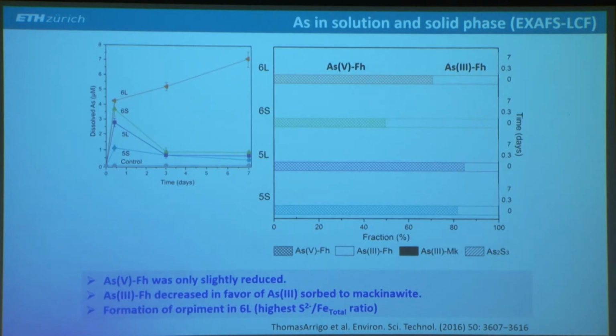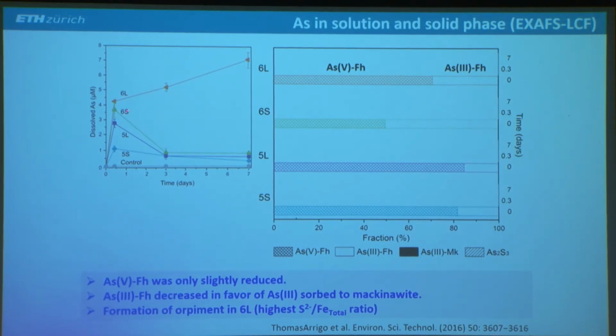If we look at arsenic, we also see a fast increase in dissolved arsenic in solution in all 4 flock samples. But in 3 samples, it decreased again. In the control, there was no arsenic release. And we had 1 sample where it continued to increase. We'll come back to this in a second. If we look at the solid phase speciation, again, initially we had mainly arsenic(V) and some arsenic(III) adsorbed to ferrihydrite or to some iron oxyhydroxides.